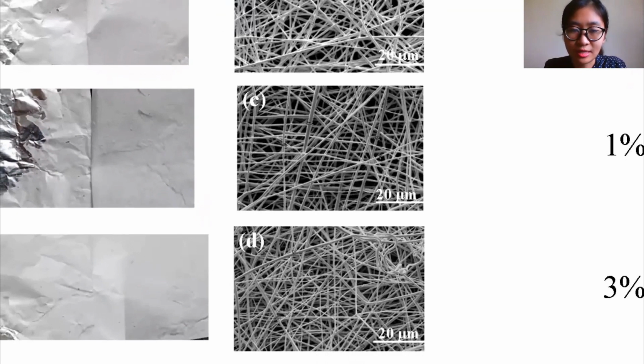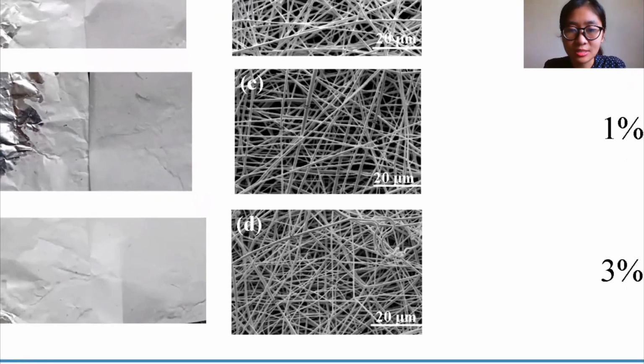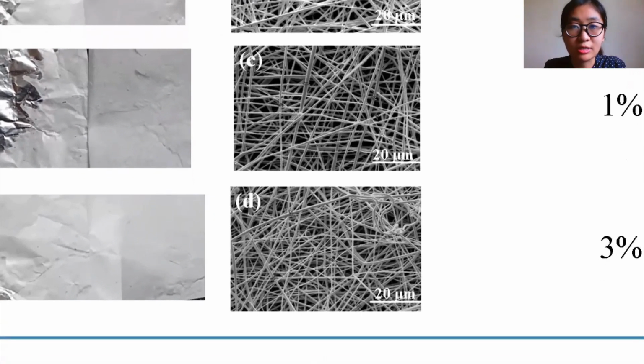This may have been due to the increase in viscosity of the polymer solution, which affects the stream jet spin and results in increased fiber cohesion points. Incorporation of the clay in the polymer matrix has caused the fibers to have branching orientations, which may also affect the mechanical properties of the membrane.